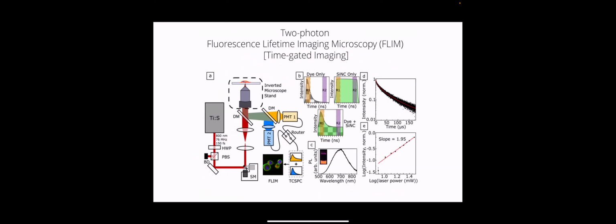So we've done some work in collaboration with Andy Dunn in biomedical engineering here at UT Austin, and they have a microscope where you can do 2 photon excitation of your dyes, and then you can do fluorescence lifetime gated imaging, or time gated imaging. So we took cells and we fed them with two dyes of different colors, both of which had relatively short lifetime, and then our silicon nanocrystals with long lifetime. And the color of one dye overlapped with, or was the same as, the silicon nanocrystals.